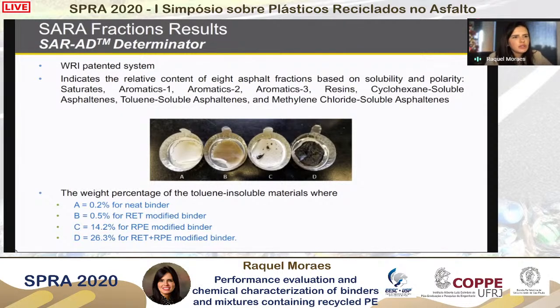And here in these pictures we have some of the resulting precipitate that we obtained from each material after evaluation with toluene as a solvent. We can see that on picture A, we have the neat binder that shows only 0.2% of material as being insoluble. Then we have B, the binder modified with the terpolymer, which gives us 0.5% of insoluble material. Then on C, the binder modified with the recycled plastic gives us 14.2% of insoluble material. And lastly, the recycled plastic modified binder containing terpolymer gives us 26.3% of insoluble material.